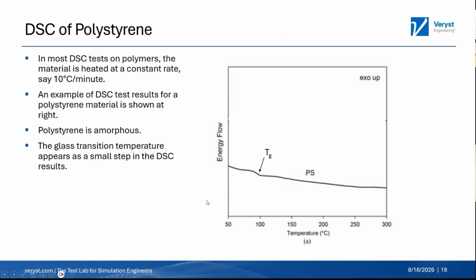To look at some actual results, this is what the actual results of a DSC trace will look like. This is a heating curve for a polystyrene sample, and polystyrene is a fully amorphous polymer. So what we see is a glass transition right before 100 C. So the Tg of polystyrene is typically around 95 Celsius, something in that range. And this is what these really look like. So this is a fairly weak signal.